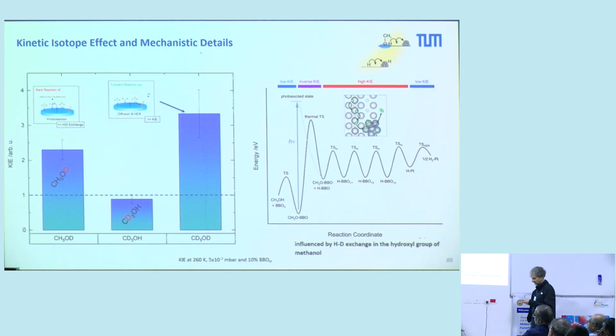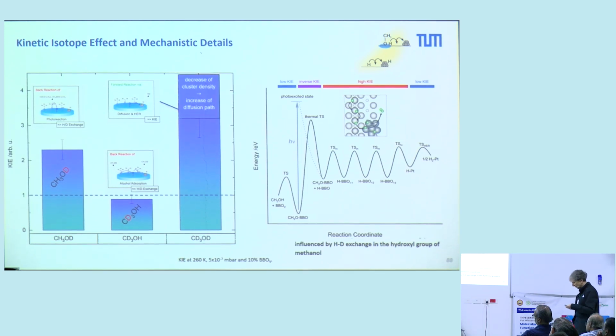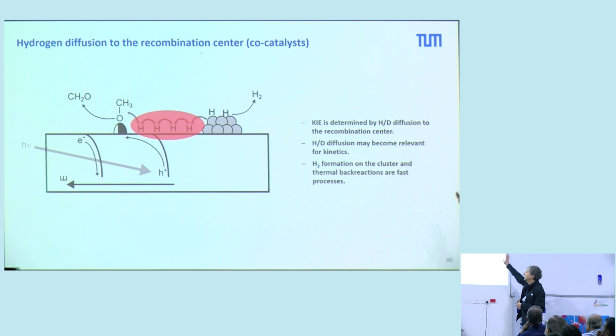In these two cases, of course, we also have the other reaction channels that are opening, these back reactions, and here, as I showed you, this H-D exchange. So these measurements show you that not only the adsorption of the alcohol and the methoxy is important in this process, but also this diffusion of hydrogen to the cluster. And this is also confirmed when we are changing the cluster density, because if you go to low densities, then you increase the distance between the clusters. You increase the diffusion length, and we have a higher kinetic isotope effect. This is another indication that this diffusion is indeed relevant. This is again summarized in this slide.